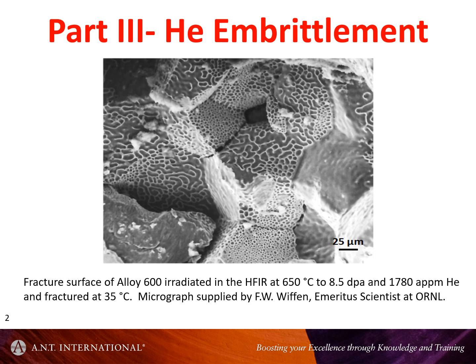And it seemed that could be attributed to helium, because at the end of life, these things are projected to have something like 30,000 atomic parts per million of helium, which is a lot. And that's a peculiarity of the CANDU reactor, because it's a very highly thermalized reactor, because it runs on natural uranium. And so it needs a lot of thermal neutrons.